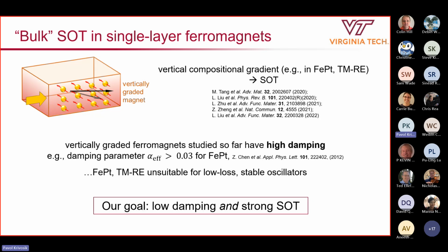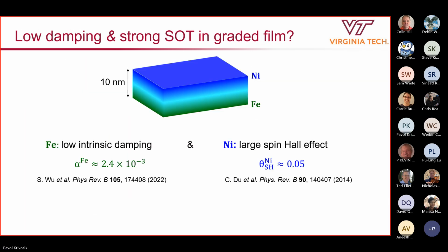All right, so again, we come back to this goal of trying to achieve both low damping and a strong spin orbit torque. So in order to pursue this goal, we opted to investigate this particular seemingly simple combination of two ferromagnetic elements. Right. So first of all, we chose iron due to its very well-known intrinsic damping. In fact, it has the lowest damping among the elemental ferromagnetic metals. And for the other element, we have chosen nickel, which again has the strongest known spin orbit coupling among the three elemental ferromagnets.